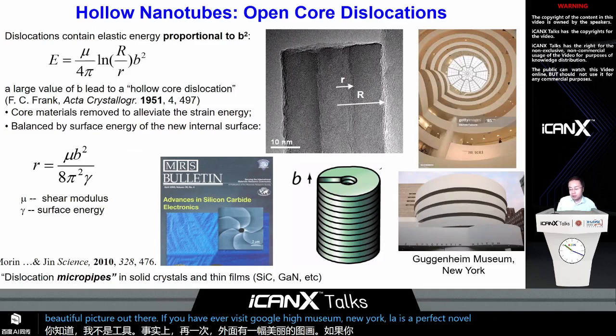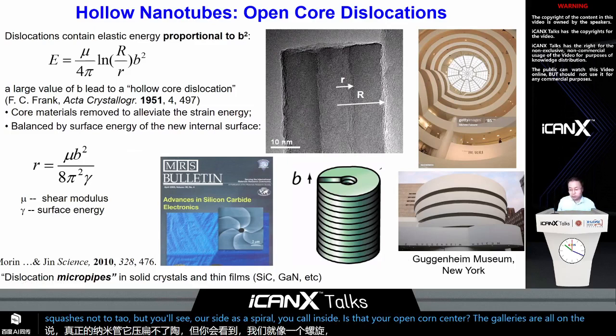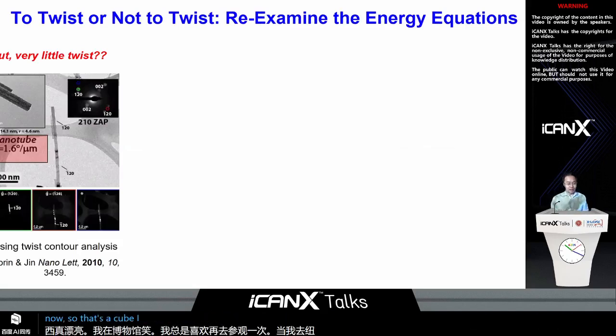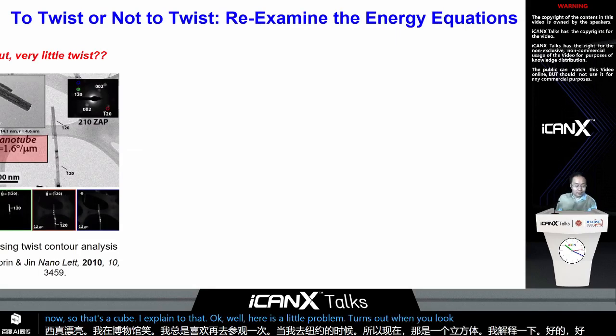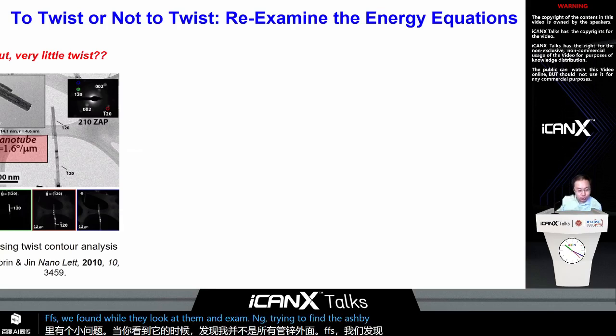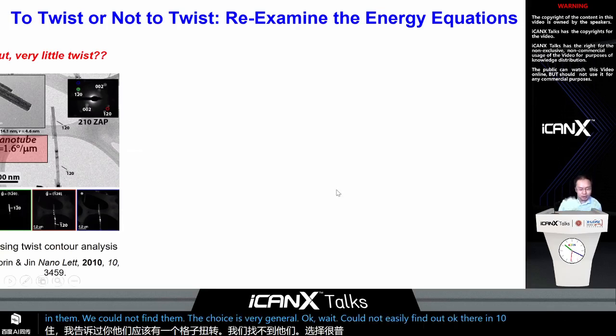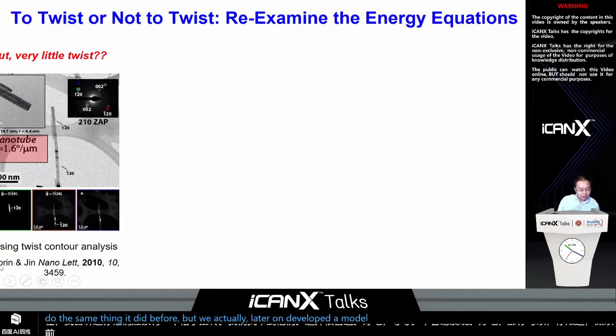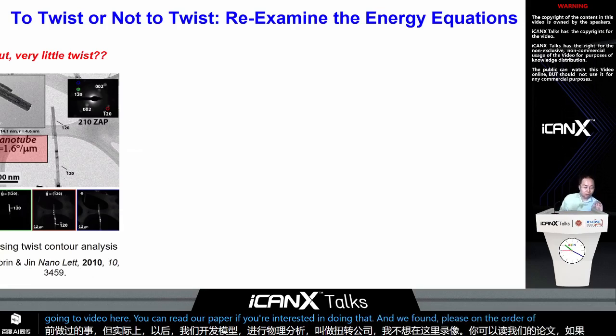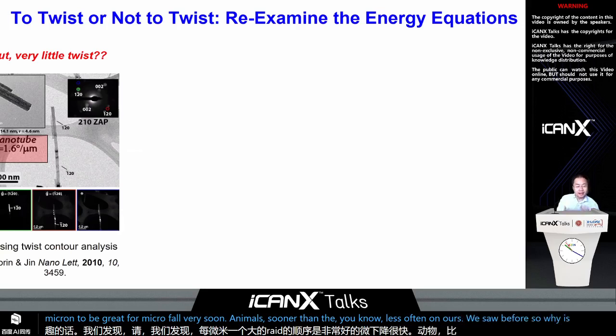This is a common phenomenon in materials science. Materials like silicon carbide and gallium nitride, if you don't grow the wafers very carefully, will have a hollow core of a few microns — a big problem for those materials until people learned how to suppress it for power electronics applications. Coming back to nanotubes: nanotubes are nothing but nanowires with dislocation micropipes. They are the equilibrium preferred configuration due to energy minimization — the material wants to minimize total energy, so it makes them hollow. There's a beautiful architectural analogy: the Guggenheim Museum in New York, with its spiral ramp and open core center, is a perfect model of a dislocation nanotube.